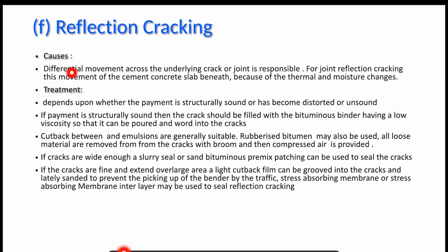Another cause can be the differential movement and the thermal cracks. If the underlying layer is made up of cement concrete, then the thermal stress that is generated in the bottom layer may propagate to the top layer, which is a bituminous course, and reflective cracking can happen. And the differential movement between two layers can also lead to generation of reflective cracking.